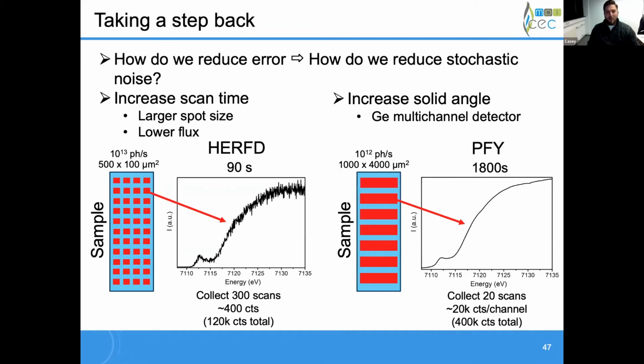Now, if we increase our scan time, we can reduce that stochastic noise. On the other hand, increasing the scan time means that we really would have problems with damage. And so if we want to reduce problems with damage, we need to spread those photons out over a larger spot. And not ideally, but a lower flux can also help reduce damage. Another big part of this is increasing the solid angle. The solid angle you can get by closely bringing in a germanium multi-channel detector will be a bit larger than what we can get ideally out of an X-ray emission spectrometer. And so with comparable total collection times, but much slower for the partial fluorescence yield, I'm getting a little bit over 3 times as many counts total for the final spectrum.